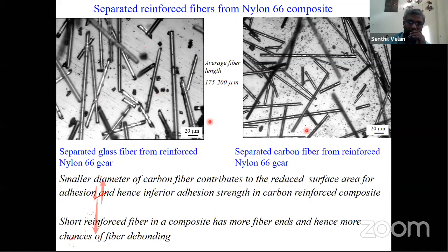And what is really the issue is, if you want to maintain the same volume fraction or weight fraction, you have to put in more fiber. Because it's a smaller diameter, when you have more fiber, you will have more fiber ends. So the diameter is going to create more fiber ends, and that is also a weaker point. When the fiber end is a really crucial issue, when you have more fiber ends, it is going to contribute a serious effect, particularly the tribological or the matrix adhesion issues. So this is what is finally